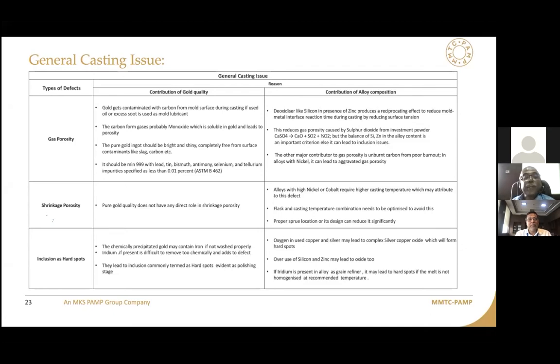Now coming to the shrinkage porosity, the pure gold doesn't have much of a value to add to it. But yes, if your alloy is having more nickel or cobalt, which requires a higher temperature, definitely it will contribute to this. And to compensate that, you have to design your sprues location correctly.